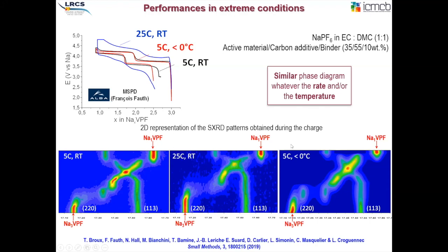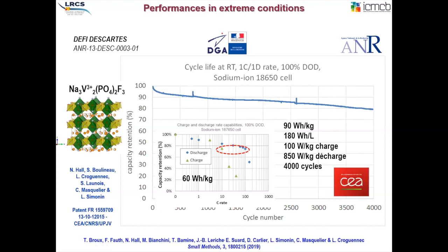We identified very early, as soon as 2015, that we could try to implement this material in real cells. And this was done in the French task force with Professor Tarascon and Laurence, Patrice Simon, Mathieu Morcret, et cetera. And with the CEA, who was able to build real cells for us, with us, and to identify that in this structure, this compound was very, very stable, in particular under very fast rates.